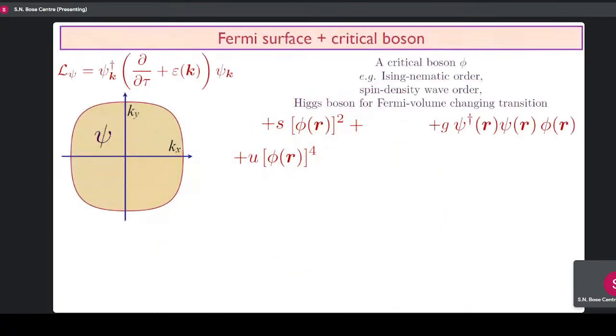So let's try to write down the field theory for this transition. If you were just doing Ising field theory, you would take some Ising order parameter phi and write down some Landau-Ginzburg potential, and then when s changes sign, you would have the phi-fourth field theory, which we know describes the Ising phase transition in 2, 3, and 4 dimensions. However, here the low energy excitations at the critical point where s goes to 0 are not just the Ising order parameter. There are also low energy excitations of the Fermi surface that are present not just at the critical point, but actually everywhere. And so we have to ask what happens to these low energy excitations right at the critical point. So you take the Fermi surface of these fermions, and then there's usually some symmetry-allowed so-called Yukawa coupling, which couples the appropriate symmetry combination of the fermions to phi. I've left out all form factors and indices, so that I could write just the combination that will couple to phi. So this is the theory you really have to study.